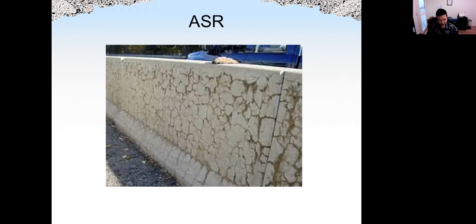All right, so ASR is one type of chemical attack. When we talked about aggregate, I think we mentioned ASR a little bit. ASR is a reaction between alkalis in cement and a certain type of silica in aggregate. Not all types of aggregate will have potential for ASR, but certain types of aggregate. This is the cracking caused by ASR. We also call that map cracking because the pattern of the crack is similar to maps. The cracking is generated from inside.